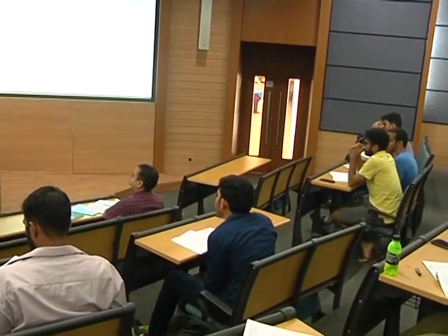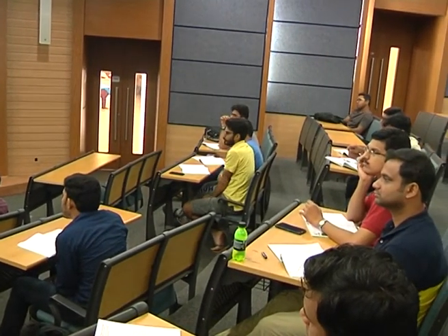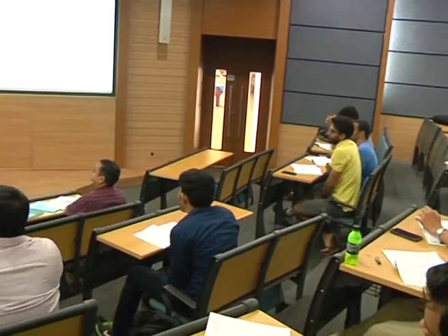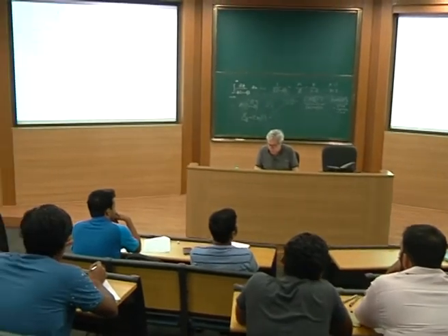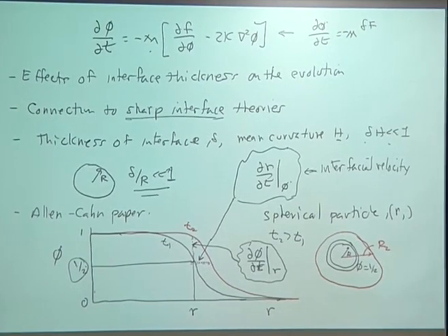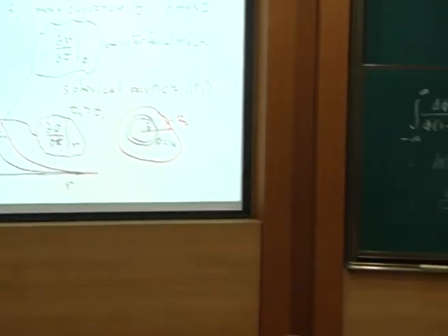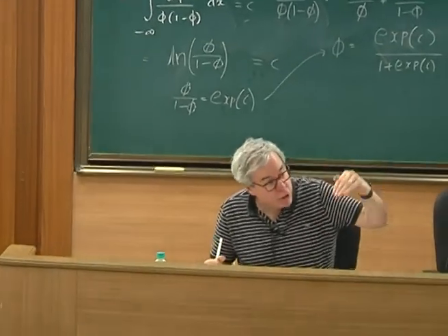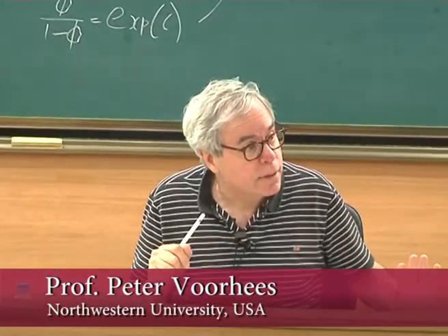Yeah. So you mean this constant M out here? Yeah. If you look at the Allen-Cahn equation, that's a good question. It sits outside because it looks like that, and it just looks like that because it's non-conserved. And so you just go down gradients in phi, the energy surface, and you don't have any spatial gradients to worry about. It's not a conserved equation. So that's an important idea.